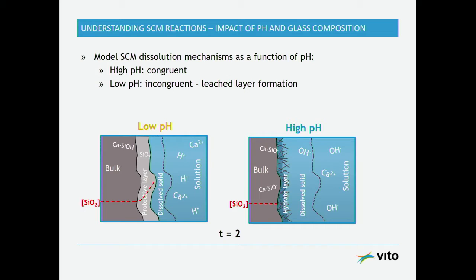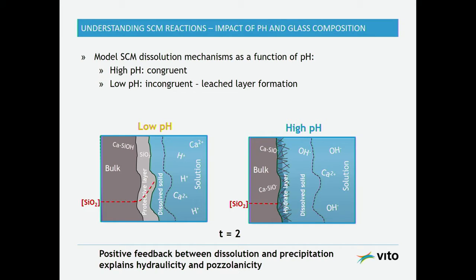Okay. And then at higher pH, instead of having the leached layer acting as a protective layer because it becomes richer in silica, we actually have a hydrate layer being established there, so we get ongoing dissolution at longer terms. So this also explains why at high pH one can establish a system where we have hydrate formation and we have ongoing dissolution, while at low pH sometimes we have the complete stop of our reactions. So there's this positive feedback between the dissolution and precipitation, which goes through the solution composition. And this is very much something we often see, that pH or the presence of calcium in the solution can actually explain why a certain material behaves as hydraulic or pozzolanic, why it reacts at the longer term or not.